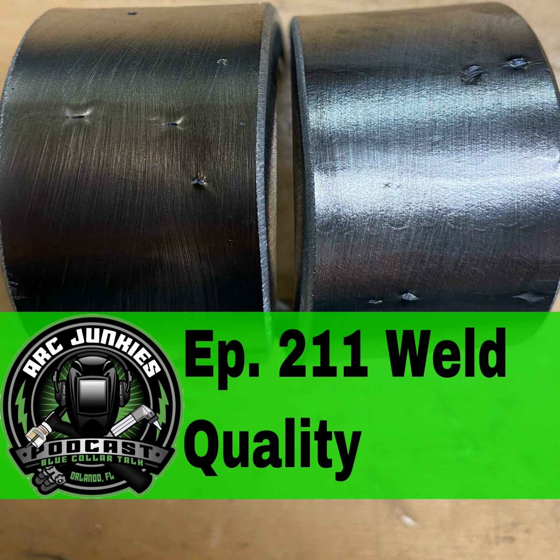So what's uniformly scattered porosity? Uniformly scattered porosity is porosity that is roughly the same size and shape, and it's scattered throughout the entire weld. So you'll probably see this anytime that you attempt to do some gas metal arc welding and you forget to turn the gas on. Or if you're running flux core arc welding and you don't have an adequate arc length or contact tip to work distance. A lot of times I'll see this if the contact tip to work distance is too small, you're going to get uniformly scattered porosity because you're kind of burying that wire in there. You need to give that wire a little bit more time to preheat before it enters that weld puddle so that it can do its job.